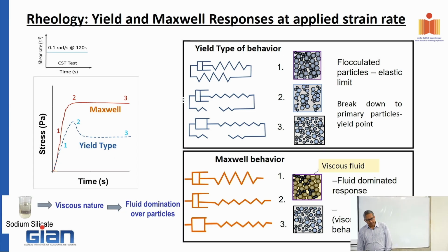Sodium silicate. I would be adding more silicate, and that's how I increase my silica concentration in the solution. Right. So if I do this constant strain rate experiment again, this is what we said is a yield type behavior. I go from step 1 to step 2. This is where the material yields, and then it starts to flow.